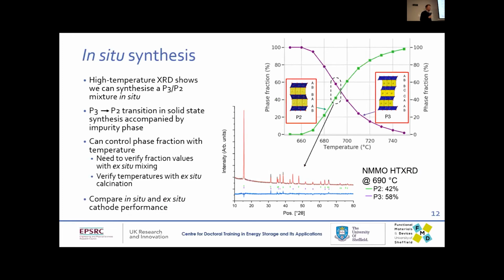So this is using some high temperature XRD data. What I did was start with this acetate dextran solution, dry it, and do this pre-calcination step, because heating it up to 300 degrees is this huge volume expansion, which wouldn't do very well in a high temperature XRD. We'd get a big mess everywhere. So pre-calcine it to 300 degrees, grind it up, stick it in the XRD, and then heat it from 650 degrees to 750 degrees. And then you can monitor the phase change as it heats up.